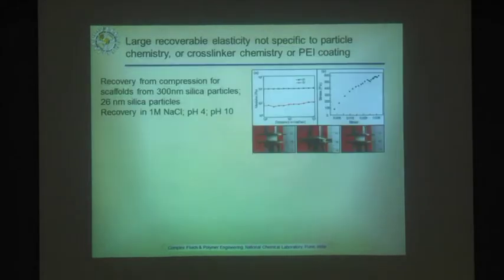Okay, so this kind of material is not specific to silica. Samajit was asking me about this, but we've made this from a wide variety of particles. I've shown you examples with polystyrene and silica. We can make this with pretty much any particle. It's independent of the particle chemistry and independent of the particle size. We see the exact same behavior whether you have a 1 micron particle or a 25 nanometer particle.